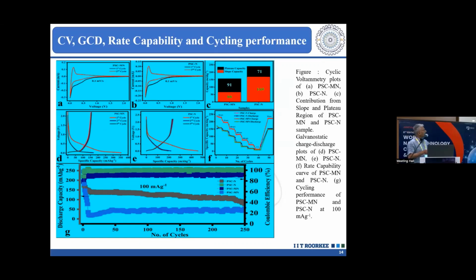Now, when we talk about the rate capability or the charging, this is cyclic voltammetry. This is current versus voltage of this material, we have the first cycle, then the second cycle, and then we can notice that with the number of cycles, this hump is gradually vanishing. So that means this hump comes from the SEI, the solid electrolyte interphase layer, and the oxygen group present on the surface. So when the oxygen group is gradually eliminated, then a smoother curve comes.